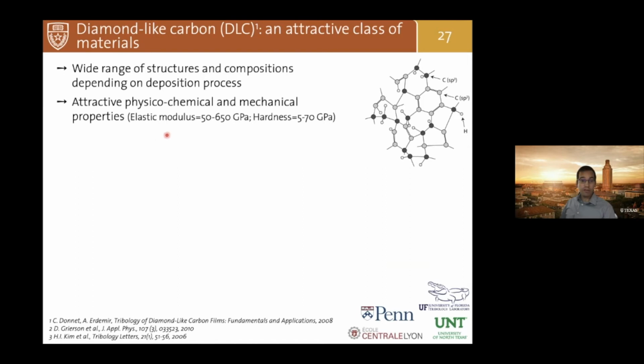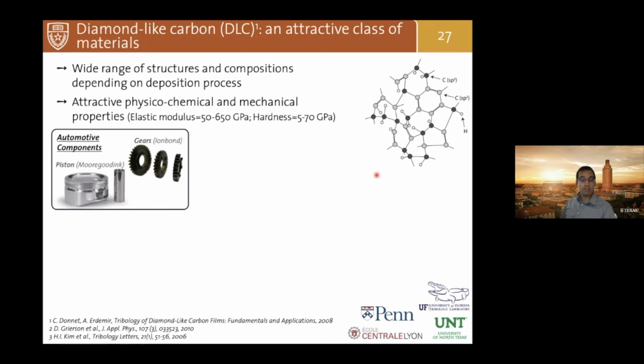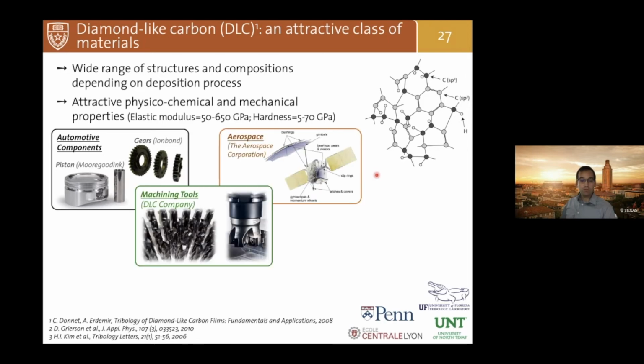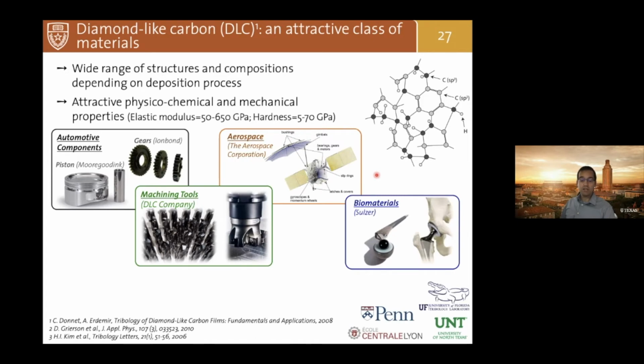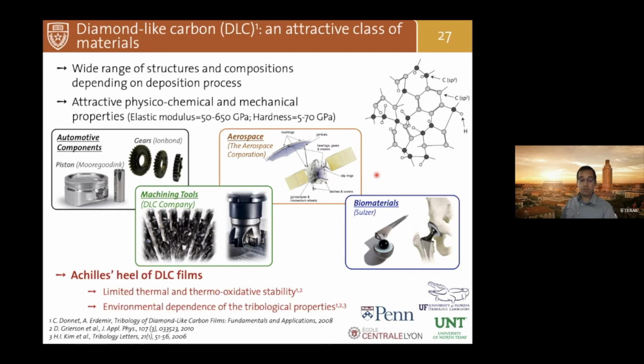For those of you who are not familiar with the term, diamondlike carbon is a very well established class of thin film materials whose success derives from their attractive physical, chemical, and mechanical properties. They consist of an amorphous network of carbon atoms, and because of these properties, they have been used as coatings for automotive components, for machining tools, for aerospace applications, as well as for biomaterials, including total hip replacements. However, there are two major limitations that currently hinder the use in a wider range of applications. The first one is the limited thermal and thermo-oxidative stability, and the second one is the environmental dependence of friction and wear. We have done extensive work also on the second topic. Today, I'm only going to focus on the first topic.